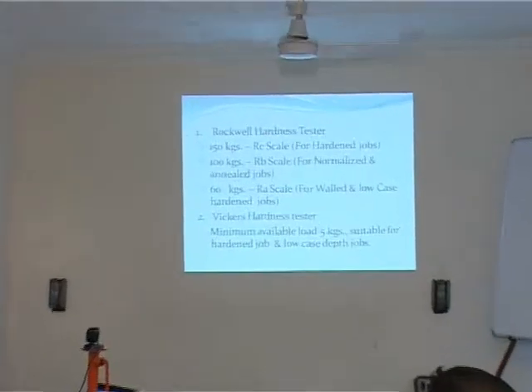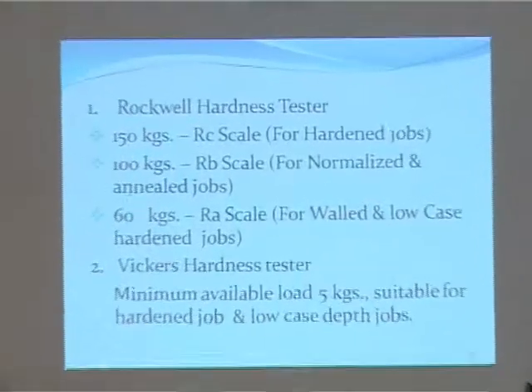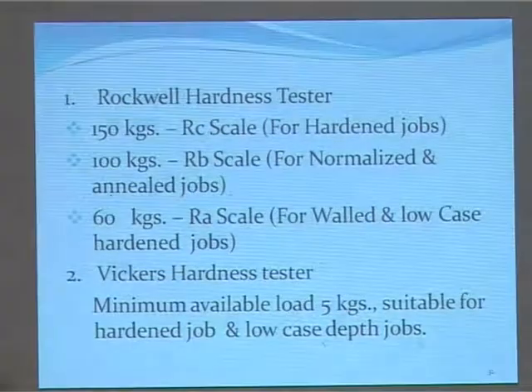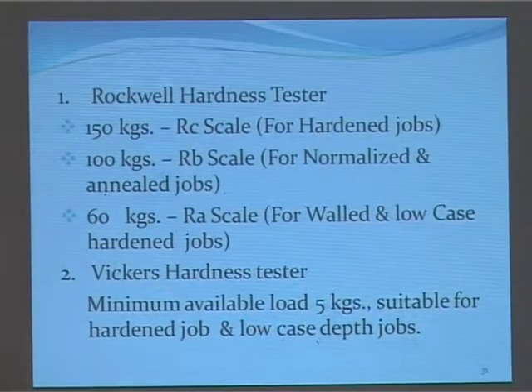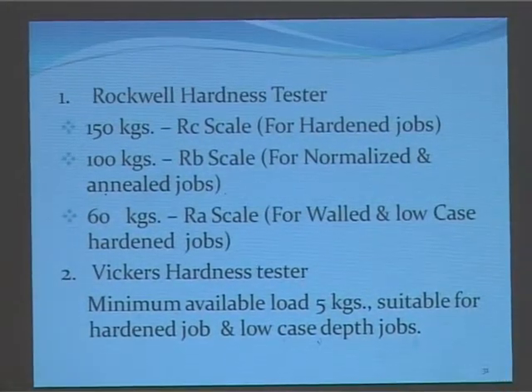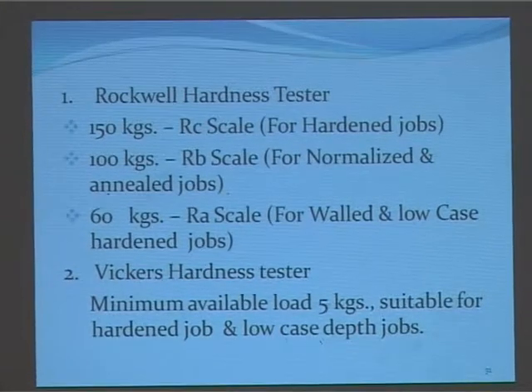When case depth is very low, do not check with RC because at 150 kg load, the diamond indenter will go inside and will not check surface hardness, but it will check the core hardness. And there will be fights between production and quality control.